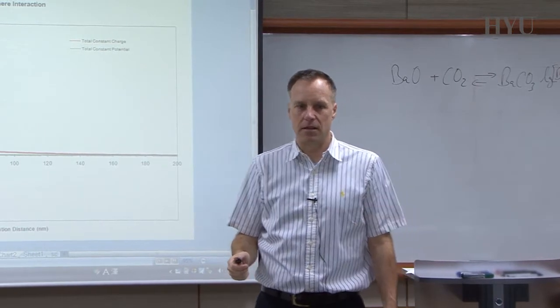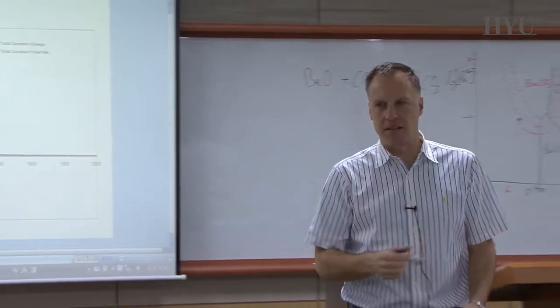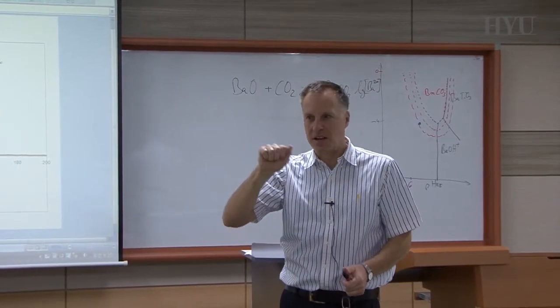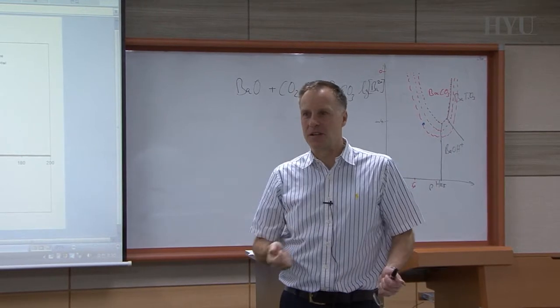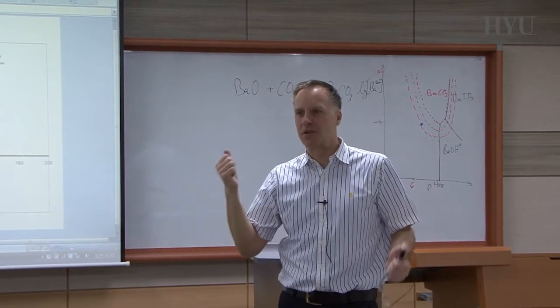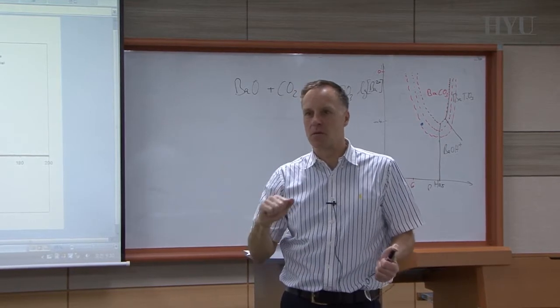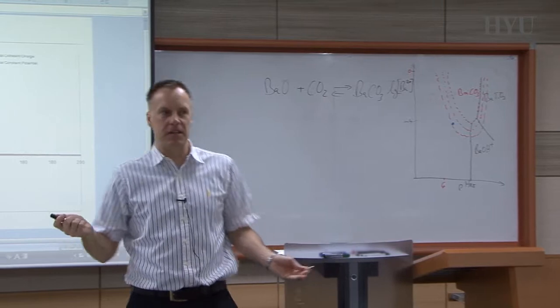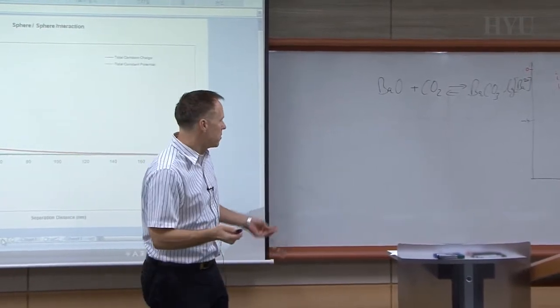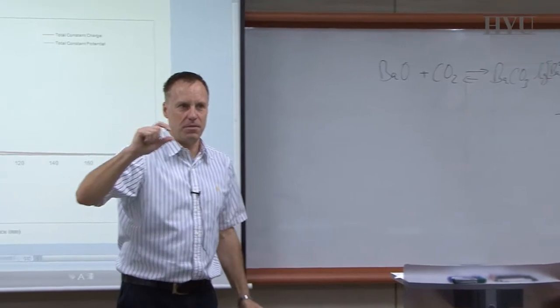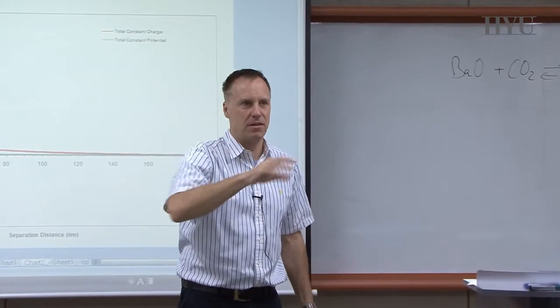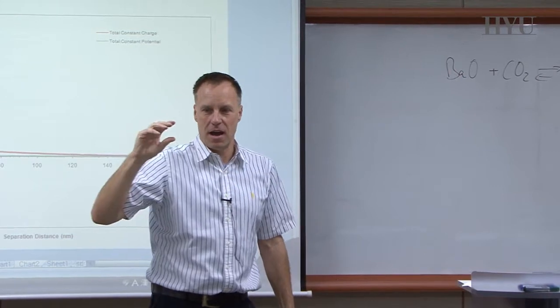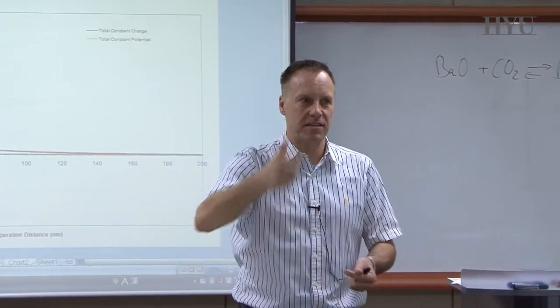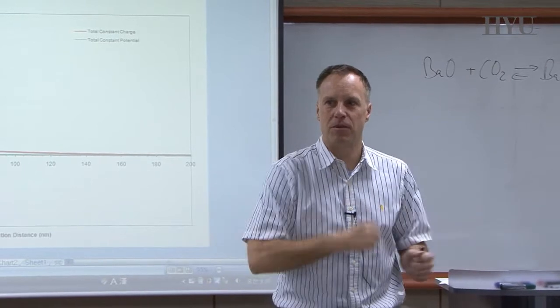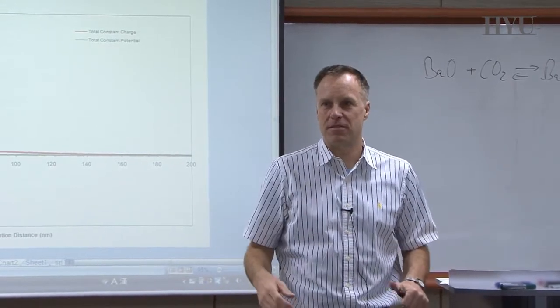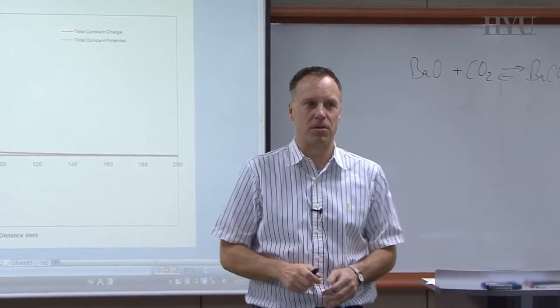And if you heat a little too fast, you get too much carbon dioxide evolving, and then your part is lost. And in industry, of course, heating is not done in the lab where you have fine control. In industry, you have big burners, you check the temperature, and it can easily happen that the temperature overshoots a little bit at one point, and then you lose an entire batch of really expensive material. And once you actually made all these capacitors, you have, in some cases, even platinum, silver, barium titanate, and so on in there. That's really expensive material, and to recycle it, to separate it and start from new again is very expensive. So you don't want to mess up the process.